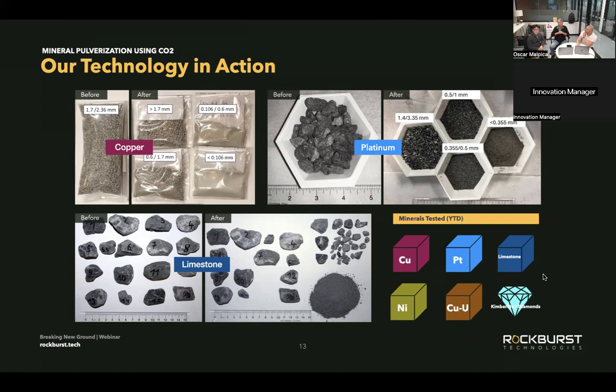So do you want to add a little bit of detail on the diamonds aspect, why our technology might be quite useful? Well, yeah, I mean, our technology, we obviously have this hypothesis, which is supported by literature for tensile breakage, that minerals will break along grain boundaries, and thus you can liberate those minerals very cleanly along all their different grain boundaries. And of course, that applies to all these metal types, but specifically for diamonds, there's a concern in the industry of breaking the larger diamonds in the milling process. And so obviously for value, you want to keep the large diamonds as large as possible as you're doing the extraction. And current milling processes risk breaking those larger diamonds. Our process, however, would tend to release the diamonds at their natural size, no matter what size they are. And thus you would retain all the value of those larger diamonds.